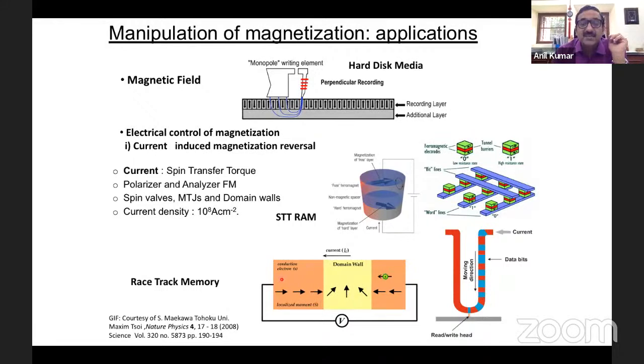Separating these two magnetizations, there is something called a magnetic domain wall. These spins exert a torque on this material, and then it pushes this magnetic domain wall. Finally, if I push this magnetic domain wall completely to the other side, my entire material is magnetized in this direction. Now, if I push this magnetic domain wall extremely to that end, then I magnetize in that direction. So that means it was shown that it is possible to switch the magnetization from one state to the other state by passing electrical current, spin polarized current, through the material.